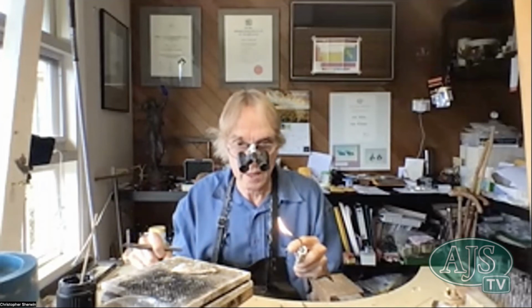If that was, say, a $50,000 sapphire, or it was absolutely irreplaceable, I would not put it through the fire, because sapphires contain inclusions that are liquid and gaseous, and they can expand and shatter the stone. So there's a lot of experience required when you work with gemstones. I guess I'm lucky. After 40 years, I've gathered a bit of grey matter in between the long hair.